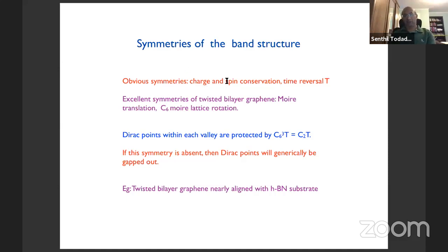And so these are the obvious symmetries, but it turns out there's a large number of excellent symmetries of twisted bilayer graphene at small twist angles, which is what we're interested in. First, there's Moiré translation symmetry. Even though there's not an exact microscopic symmetry, it turns out to be an excellent symmetry as far as electronic physics is concerned. That's what I said right in the beginning slides. Momentum is a well-defined quantum number at low twist angles. There's also a C6 Moiré lattice rotation, which is a good symmetry at small twist angles.